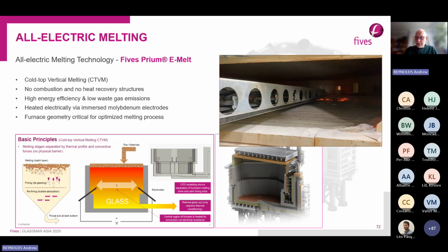So all-electric melting technology is a little bit different. Here we don't use combustive energy input. We melt the glass electrically by passing current through the glass. We have molybdenum electrodes immersed in the glass through the refractory containing tank, and we pass quite large currents through the melt, and we heat the melt with the Joule effect, resistive heating.